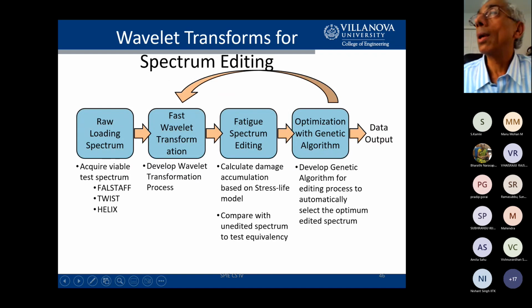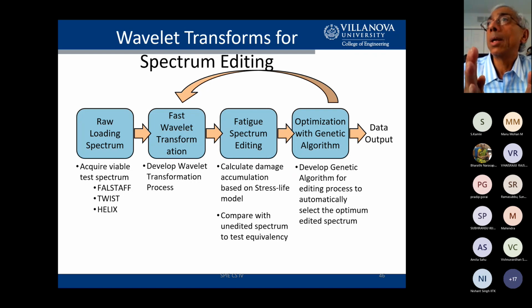So here's the approach we're taking for what's called spectrum editing. Spectrum editing is taking the huge spectrum and then compressing it so that you have fewer cycles to deal with, and therefore your testing can be done quicker, and the costs are reduced. But simultaneously, if you're going to scrunch the spectrum down to a smaller portion, you want to make sure that you're not compromising anything. And so the compromise, if you do it poorly, is that the damage you introduce in your component when you've got an edited spectrum might be very different from the damage that you get if it was subject to the full spectrum. And so it's important to make sure that the damage that you get from an edited spectrum is about the same as the damage you get from a full spectrum. So if you enforce that condition, then your spectrum editing is successful.